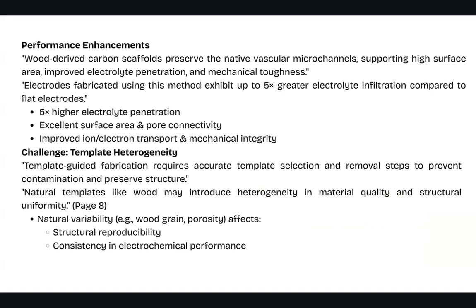So this provides performance enhancement. The wood-derived carbon scaffold preserves the native vascular microchannels, supporting high surface area, improved electrolyte penetration, and mechanical toughness. The electrodes fabricated using these methods usually exhibit 5 times greater electrolyte infiltration compared to normal flat electrodes. So what we can see from this is there's 5 times higher electrolyte penetration. There is excellent surface area and pore connectivity, and there's going to be improved ion electron transport and mechanical integrity.